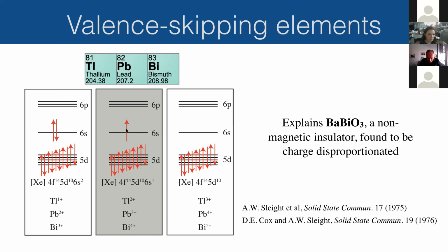So what the system does, it will happily be in this valence state or in this valence state. If you want to make a material where you would force the valence state to nominally be one of these ones, what you will have is charge disproportionation between this state and this state. So 50% will be like this, and the other 50% will be like this. It really does this in order to avoid that. And this explains barium bismuthate, which given that barium should be a 2 plus cation, forces bismuth to nominally be 4 plus. So you see that would correspond to this type of configuration, not allowed.